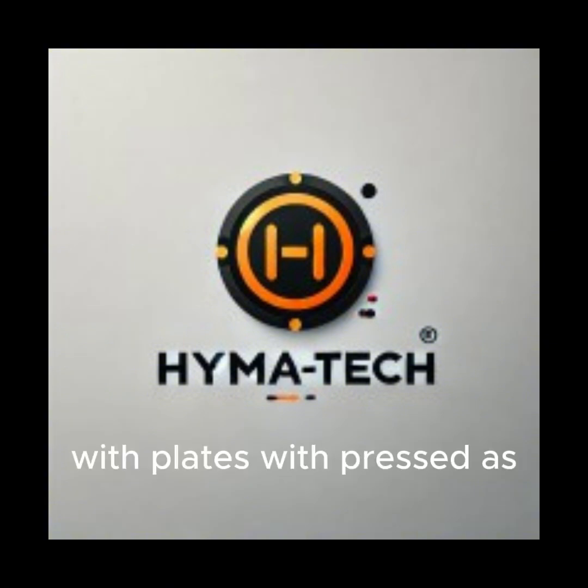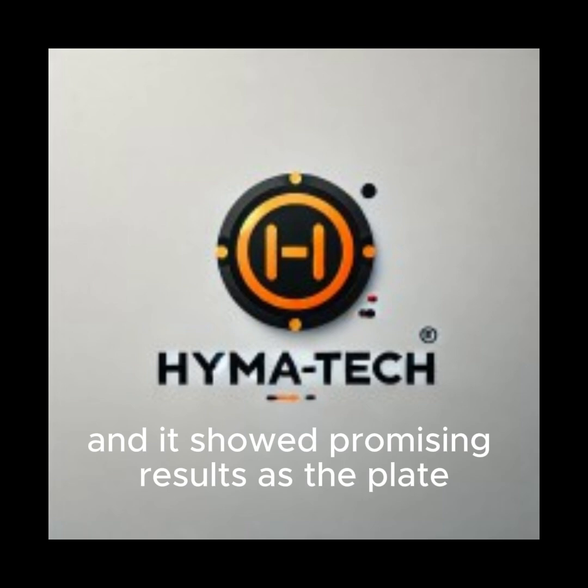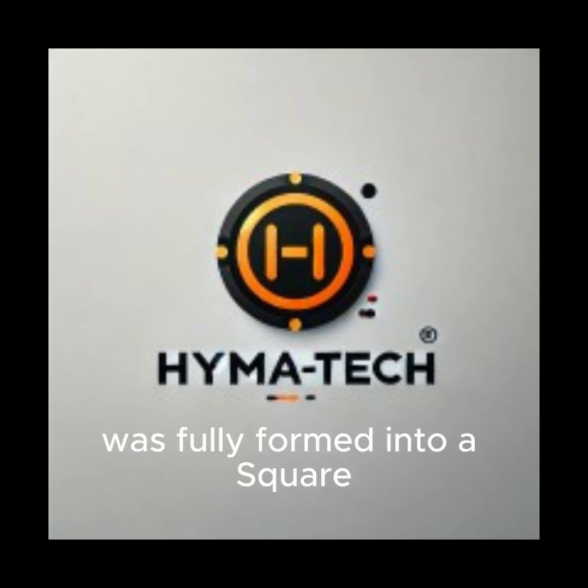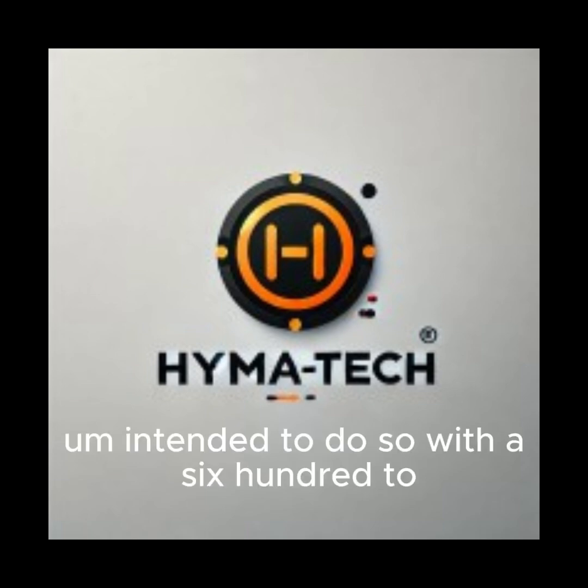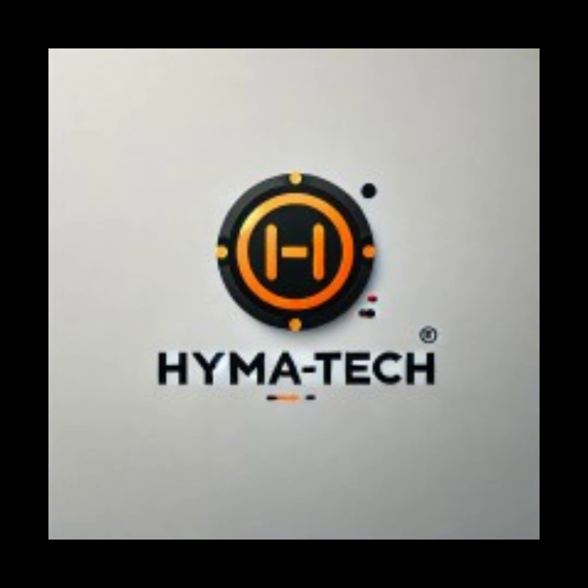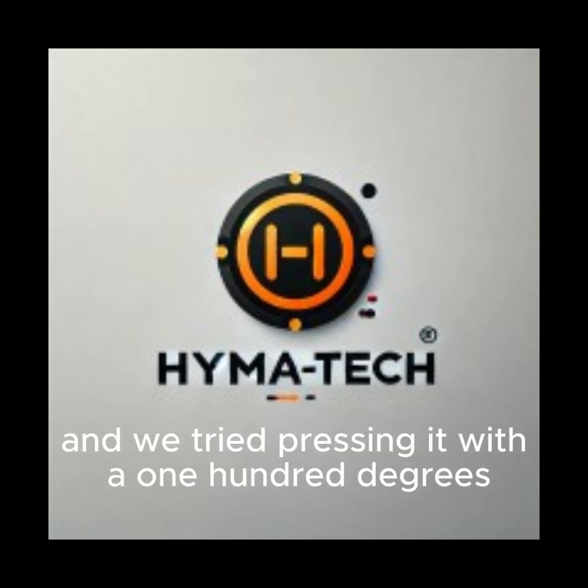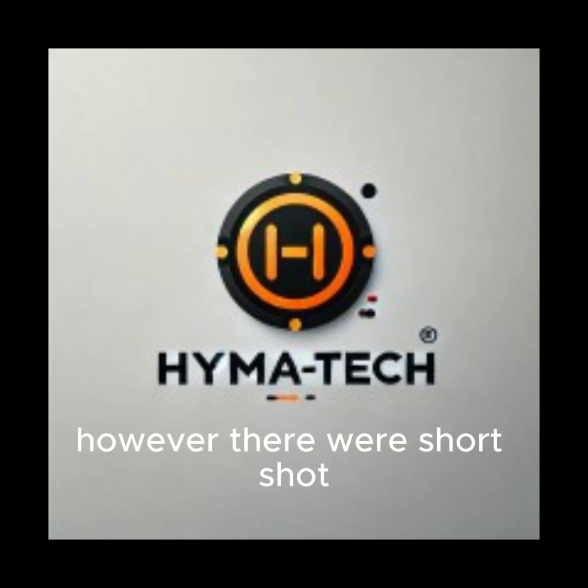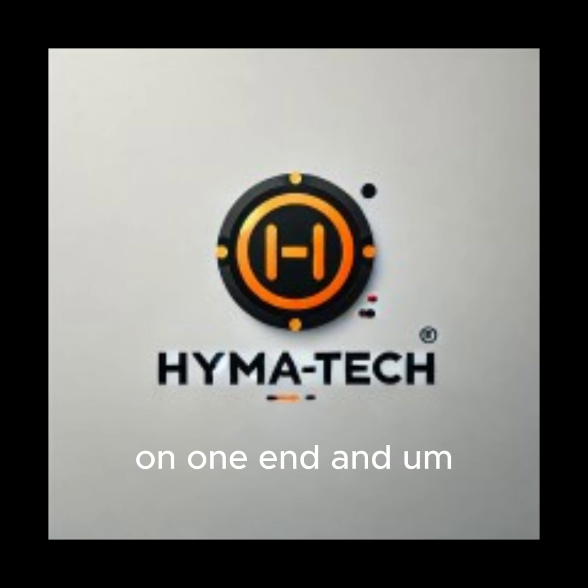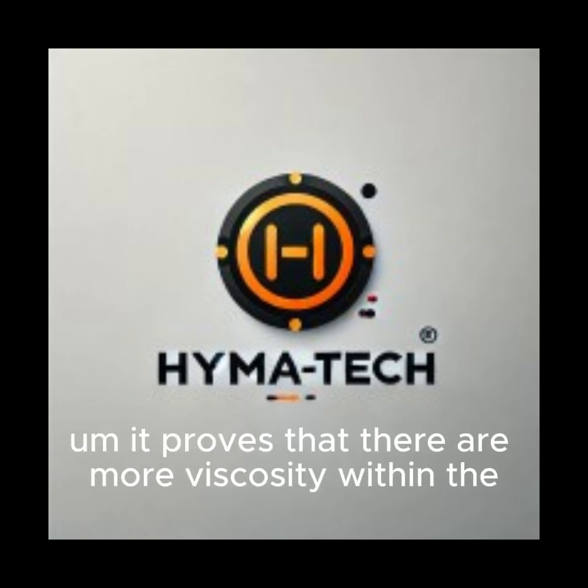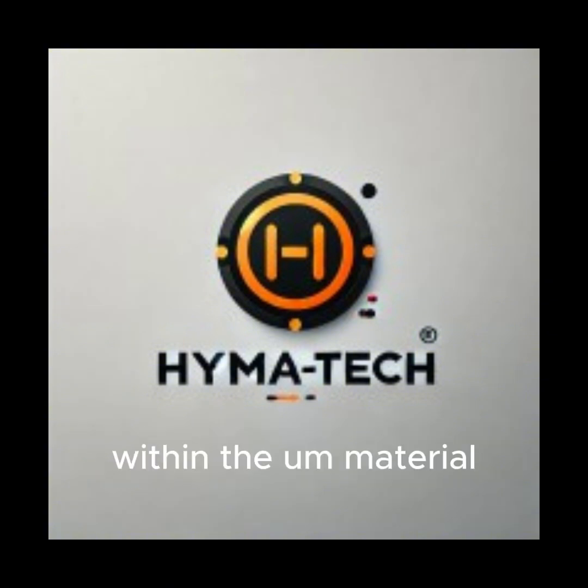And Matthew, your main project is about the heating of the mold and what effects it has on the product process. Can you tell me more about that? Yes. So we've tested pressing plates at 200 degrees Celsius, and it showed promising results as the plate was fully formed into a square, which we intended, with a 600 by 600 millimeter picture frame. We also tried pressing it at 100 degrees. However, there were short shots on one end, which shows that there is more viscosity within the material, which means it's more dense and harder for the material to flow.